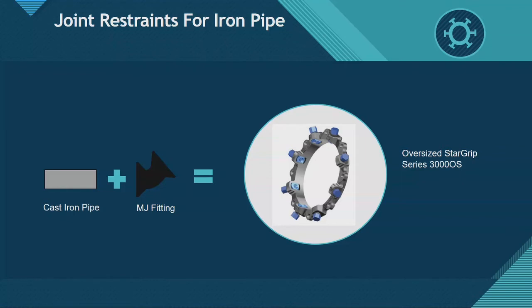When you're putting it on this pipe, though, you have to make sure the pipe is in good condition and not corroded. The biggest concern is if there's graphitization, and what that does is you can't really see it. It is a type of corrosion, but you can't necessarily see it. The pipe will still hold pressure. So with your water, you wouldn't know it was bad pipe. But if you hit it with a shovel or a backhoe, that pipe could easily break.